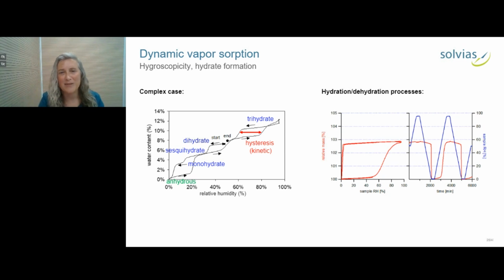So raising and lowering the humidity, you see that basically the mass change is very stable over a large range. And only when you get down to below 5% relative humidity does it convert into the anhydrous form. And then there's a certain degree of kinetic stability. The anhydrous form persists a bit and then converts into the monohydrate. But then you're going to want to know, okay, somewhere in this range is thermodynamic equilibrium. And you can find this by doing competitive suspension equilibration experiments. So you mix the two forms together at different water activities and equilibrate them until only one form persists. And then you can see what the stability range is. And such experiments showed here that the critical water activity was somewhere between 0.17 and 0.21, so corresponding to 17 to 21% relative humidity.